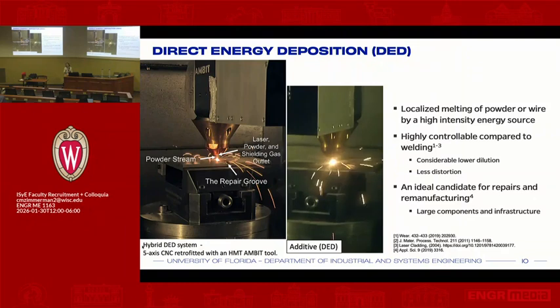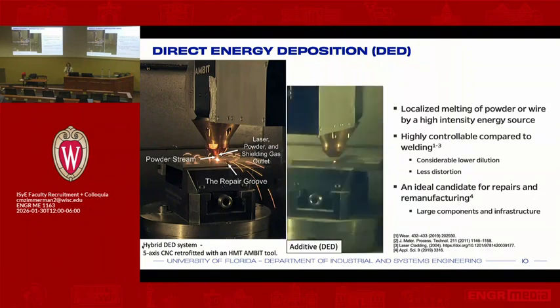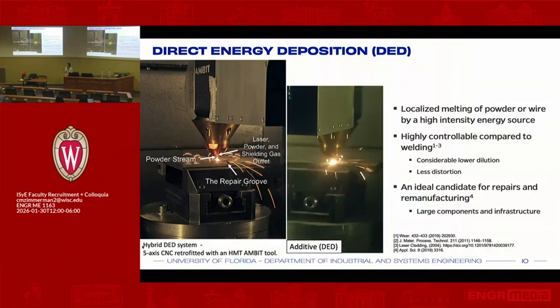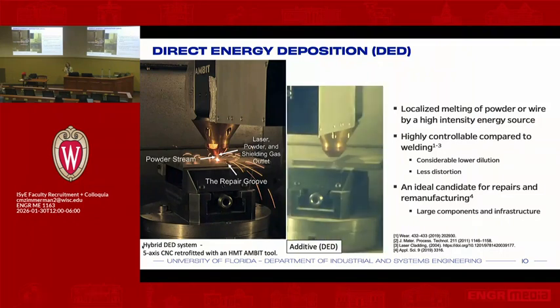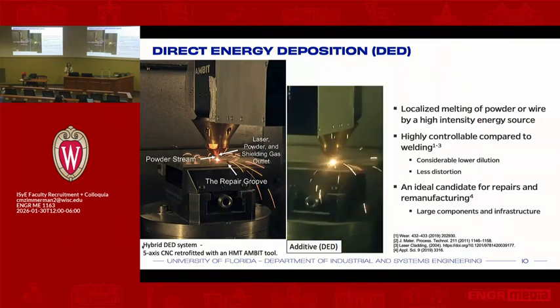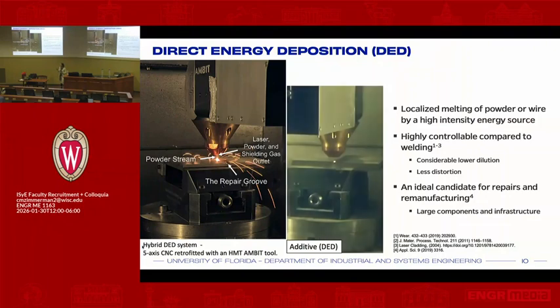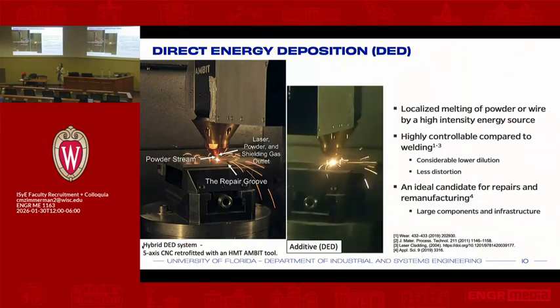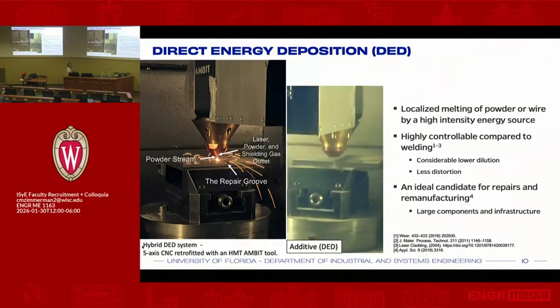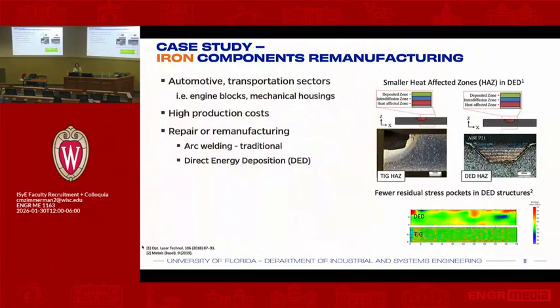Now, when it comes to the actual repair itself, what you're going to be noticing is that you're going to be generating less residual stresses. You have a very localized source of heat going into that area. When you look at the interface between the substrate and the actual deposition material, you're going to be seeing significantly less distortion. And when I say distortion, the heat affected zone is going to be very minimal in comparison to a traditional repair using traditional wire arc welding.